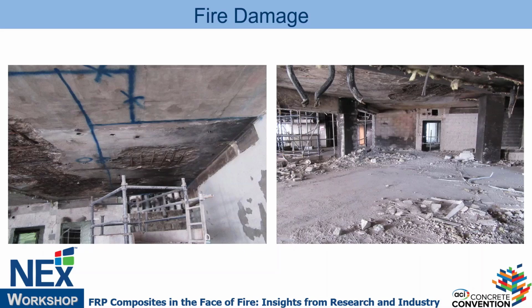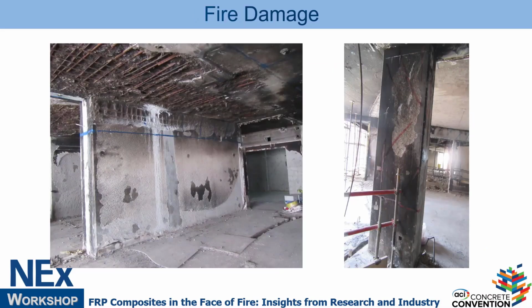But you can see between these photos, and I think these next photos, one thing that's common in most of these fires: the damage is more severe toward the top side, right? Why? Because heat rises, right? And if you look at most of them, the floor is in pretty good shape. Actually, I've seen many structures where there's significant damage, but the floor is relatively in good shape. This is something that's actually in ACI 216 right now, where it clearly says that the top side is sometimes not as critical as the underside.